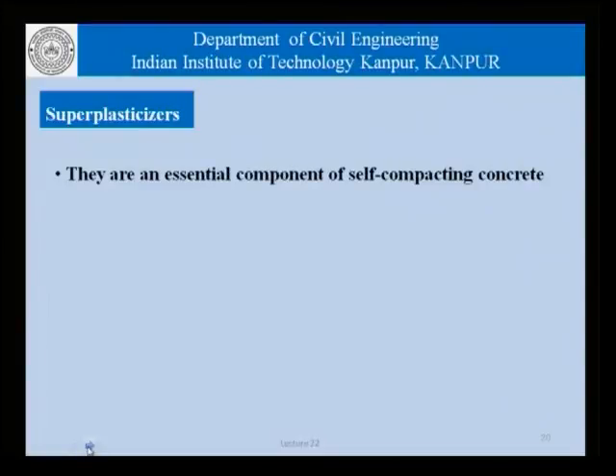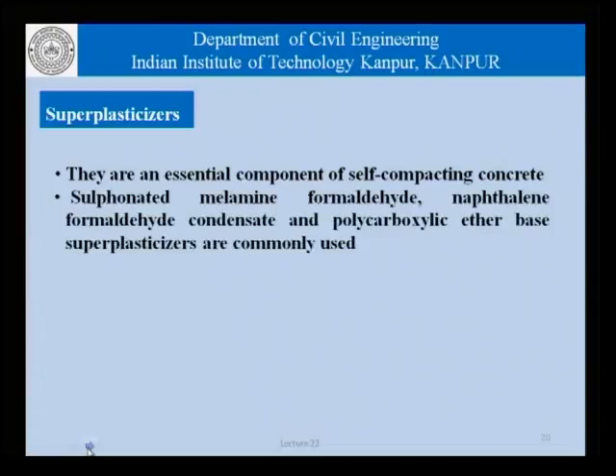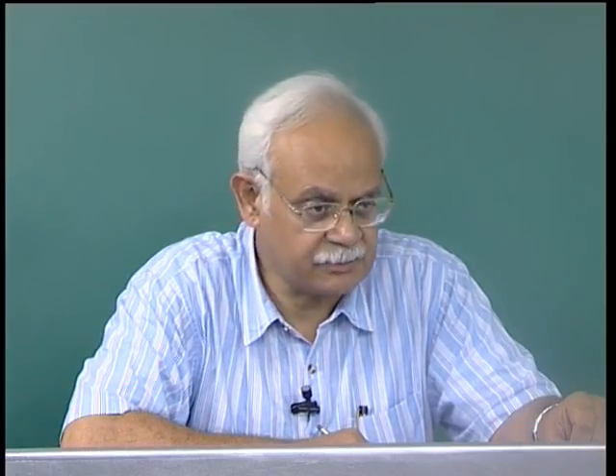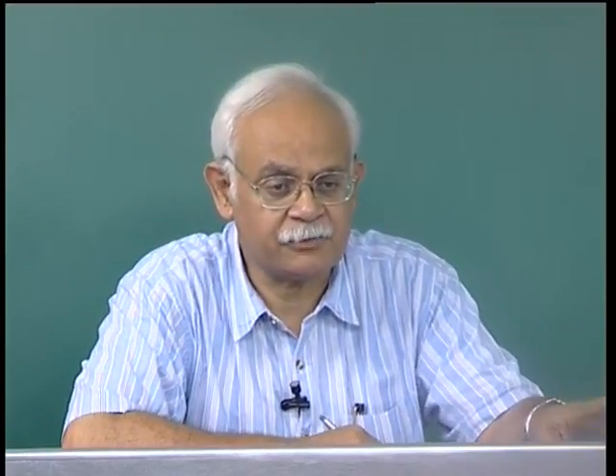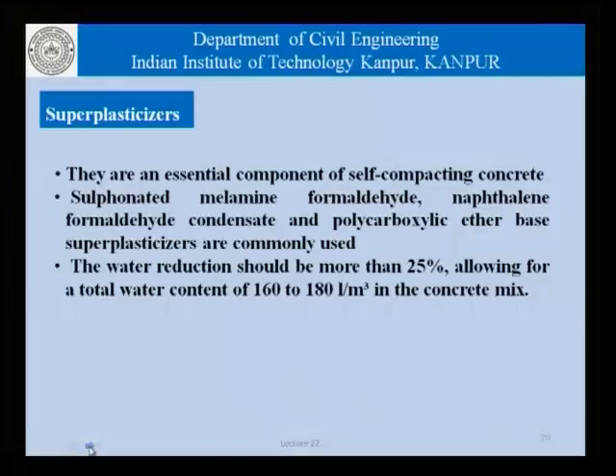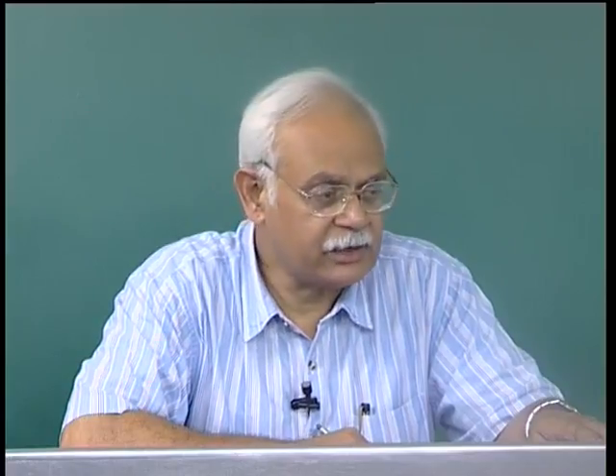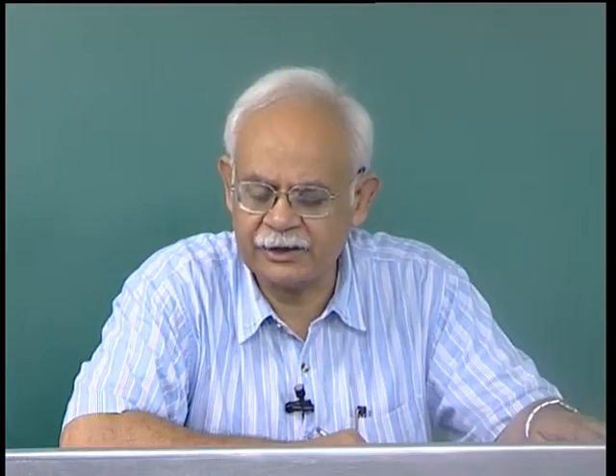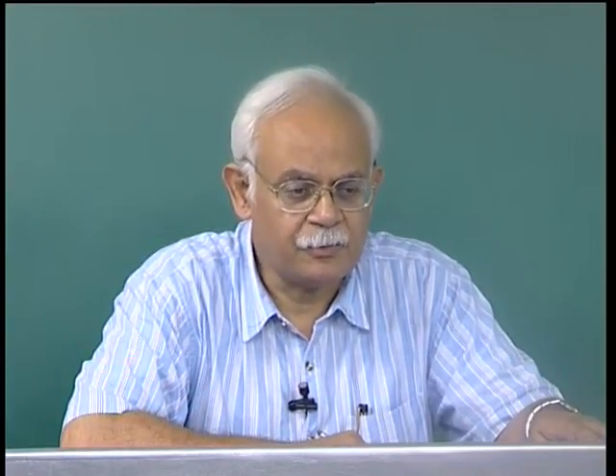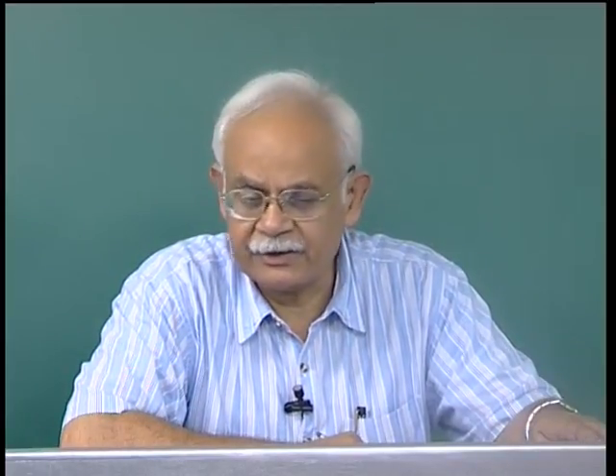Coming to superplasticizers, they are an essential component of self-compacting concrete because they help us reduce the water content. And as far as these admixtures are concerned, normal sulfonated melamine formaldehyde, naphthalene formaldehyde condensate, and polycarboxylic ether based superplasticizers are commonly used. Depending on the chemical composition of the cement, there may be issues relating to compatibility of a particular admixture with the cement and so on, and that is something which needs to be established from time to time as far as a construction site is concerned. As far as these admixtures are concerned, the water reduction achieved should be about 25% or more, so that the total content of water is restricted to about 160 to 180 liters per cubic meter. Anything more than that would make the demand on the powder content simply too high.